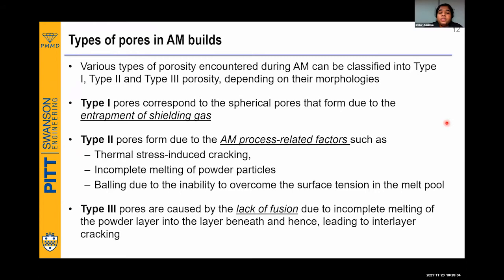And the reason I call this very dangerous is because of its shape. Type 2 pores have very sharp edges, and their size can be between a few micrometers to even millimeter size. And these type 3 pores are caused by lack of fusion. As the name suggests, they even call it a lack of fusion pore too.